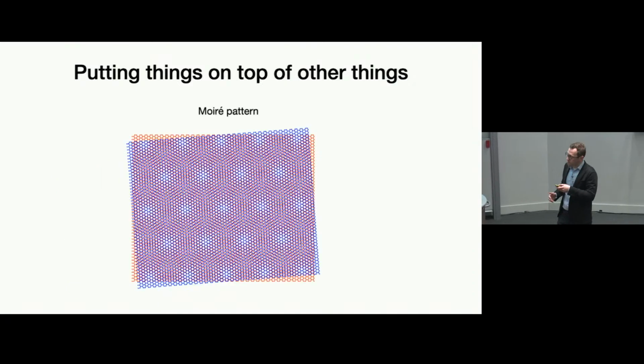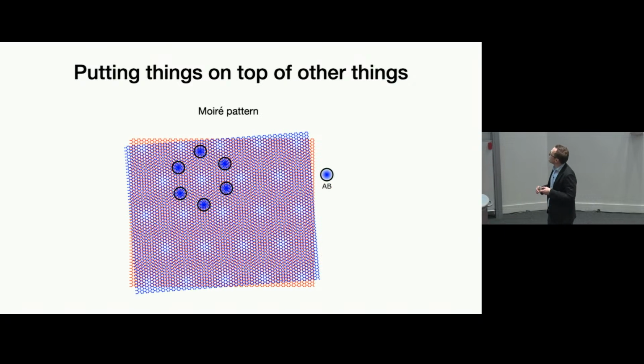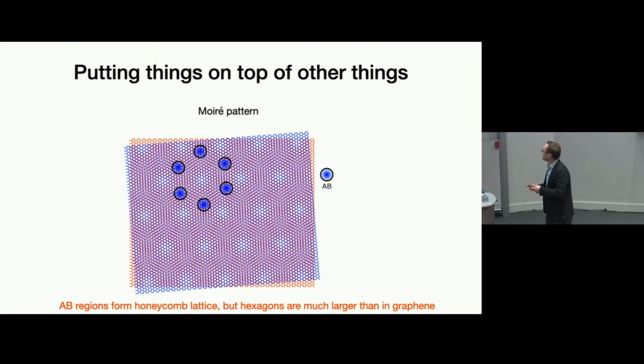If we look at this at a bigger scale, we see that actually these regions of different stacking arrangements make up a very regular pattern, which is called a Moiré pattern. In particular, when we focus on the regions of AB stacking in this Moiré pattern, what is quite interesting is that they also start to form a hexagon, much like the hexagon created by the carbon atoms in graphene, but with the important difference that this hexagon formed by the AB regions is a much larger hexagon than that formed by the carbon atoms in graphene.